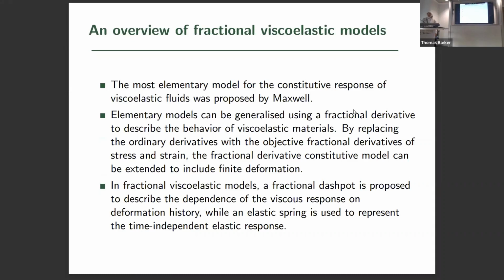Here I will give an overview of fractional viscoelastic models. The most elementary model for the constitutive response of a viscoelastic fluid was proposed by Maxwell. Elementary models can be generalized using fractional derivatives to describe the behavior of viscoelastic materials, by replacing the ordinary derivative with the objective fractional derivatives of strain and stress.